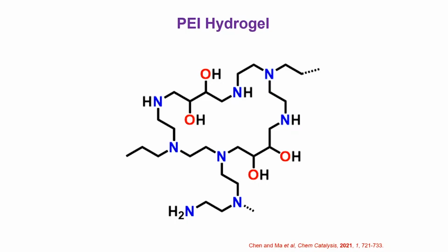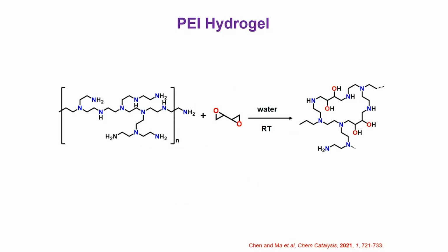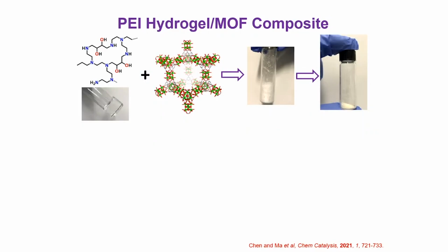What we decided to do is to take our branched polymer and link it, or cross-link it, with more hydrophilic groups. Why do we need more hydrophilic groups? We want to invite more water molecules to be in close proximity to the active site. More water molecules means your reactivity would be higher, because that's the reagent that you need. I could do this chemistry, which you could buy from Aldrich, 4% cross-linking, very quickly, and that's what you get. Once you cross-link it, you get that goo, hydrogel.